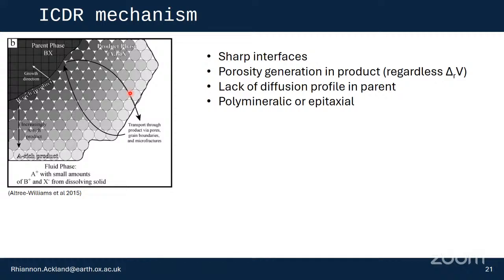The features characteristic of this mechanism are very sharp interfaces between the parent phase and the product phase. The generation of porosity is required in the product phase so that a fluid pathway is maintained between the bulk fluid and the fluid that reaches the reaction front that causes the dissolution of the parent. You also see a lack of diffusion profile in the parent mineral phase, so you'd see no diffusion profile in the cation B in this parent. And the product phase can be either polymineralic or epitaxial. If you have a high degree of similarity between the crystal structures of the parent and the product, you'd see epitaxial growth and perfect inheriting of the parent's crystal structure. But if there's a large degree of mismatch, then you get polymineralic rims instead.